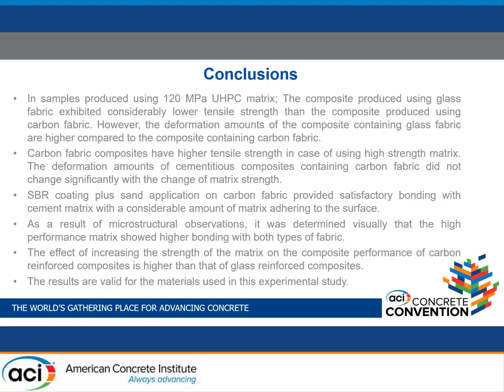As a result of microstructural observations, it was determined visually that the high performance matrix showed higher bonding with both types of fabric. The effect of increasing the strength of the matrix on the composite performance of carbon reinforced composites is higher than that of glass reinforced composites. And I have to mention that the results are valid for the material used in this experimental study.